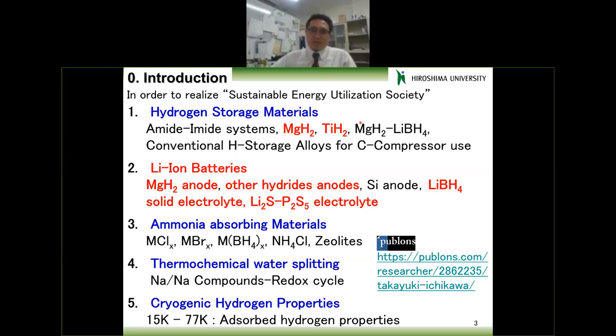This is a slightly different topic, but we focus on ammonia as a hydrogen carrier or energy carrier. Ammonia is quite well suited for transportation because it is easy to make a condensed state. At just about 10 bar pressure, gaseous ammonia can be liquefied, but that pressure is still slightly high for normal use. So we focus on ammonia absorbing materials, such as chlorides, bromides, borohydrides, or zeolites. By using these materials, we can control the vapor pressure of ammonia.